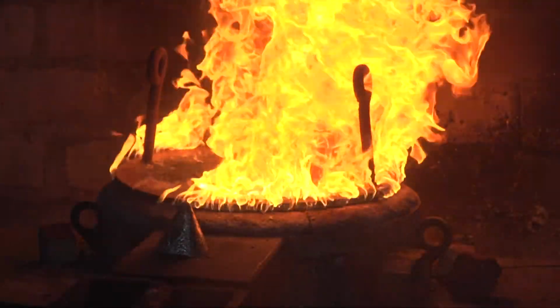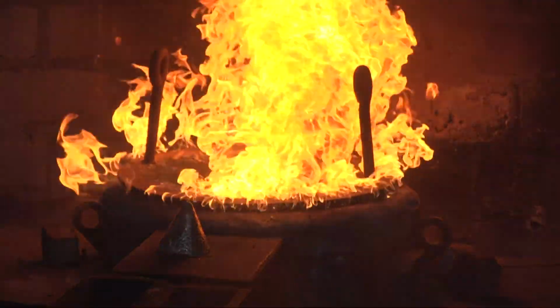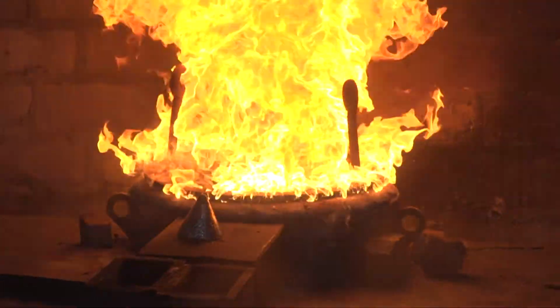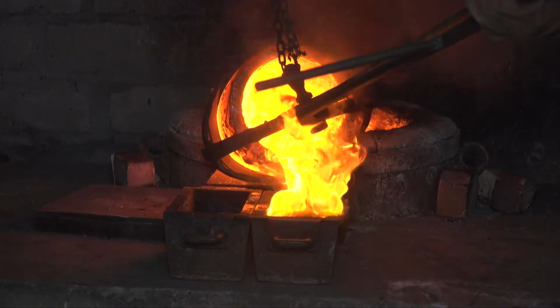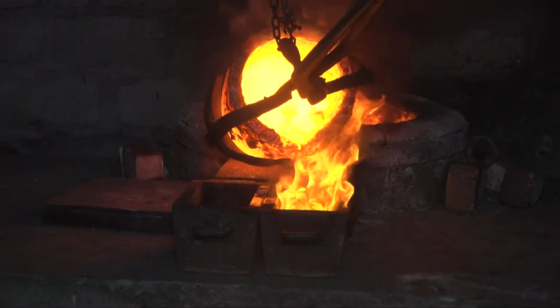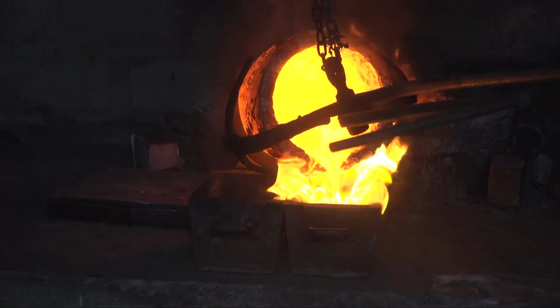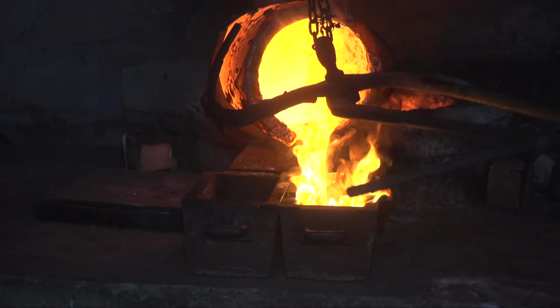The smelting process uses a gas furnace to melt the gold and burn off many of the impurities that may still be present. At this stage in the process, the gold is approximately 80% pure, with a small amount of silver and some other metals present. The pouring of a gold doré bar marks the end of a long concentration process which has taken the gold from approximately 3.3 parts per million when it was blasted out of the ground to a purity level of approximately 80%, an increase in gold concentration of over 240 thousand times.